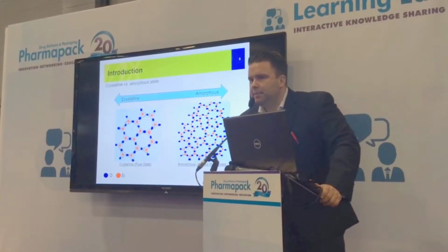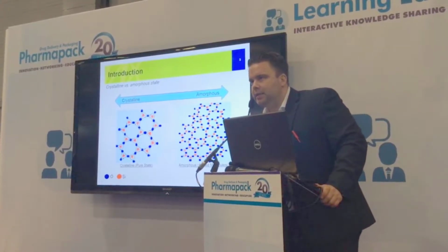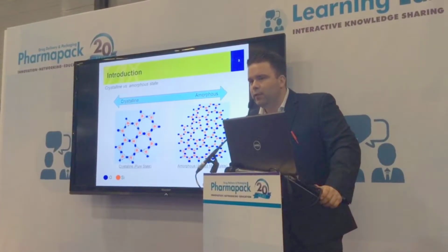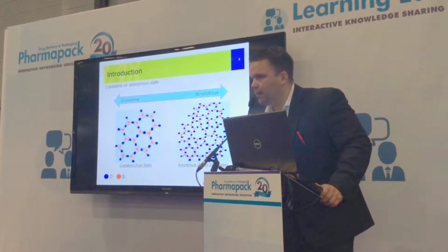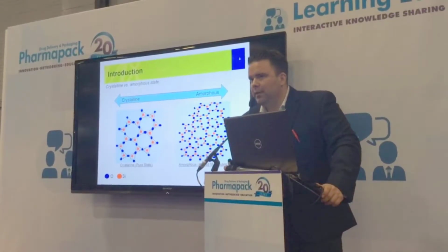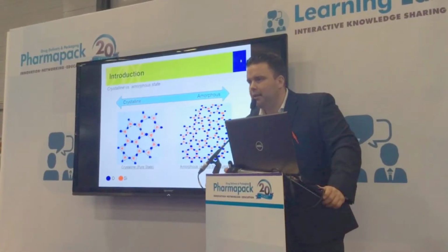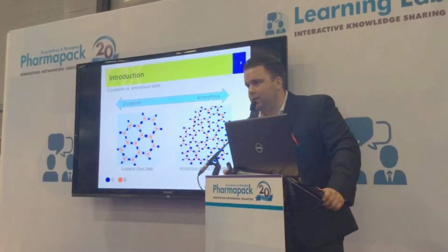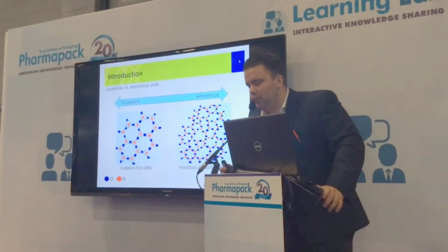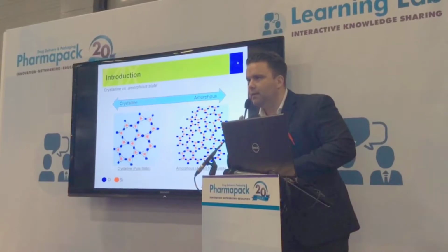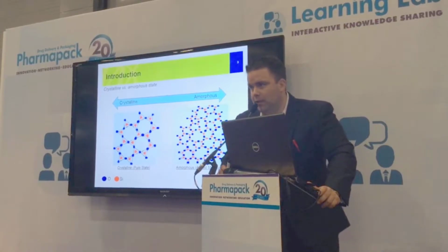So glass is mainly comprised of silicon dioxide. And when silicon dioxide is in its pure form, it forms very regular shaped four-bonded tetrahedral structures. I have this shown on the left-hand side of the screen here. The melting point of such structure is over 3,000 degrees Fahrenheit. So fabricating glassware at such high temperatures can be very challenging. Therefore, there's added modifiers and stabilizers to either lower the melting point of glass, to make glass more durable, or to even change the color of glass in regards to amber glass.